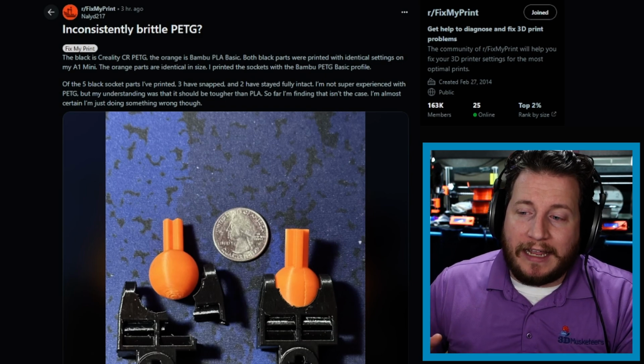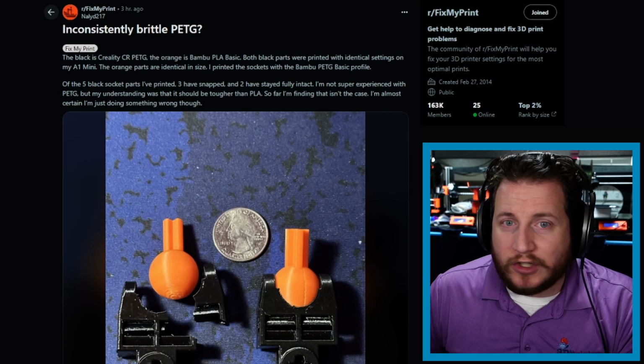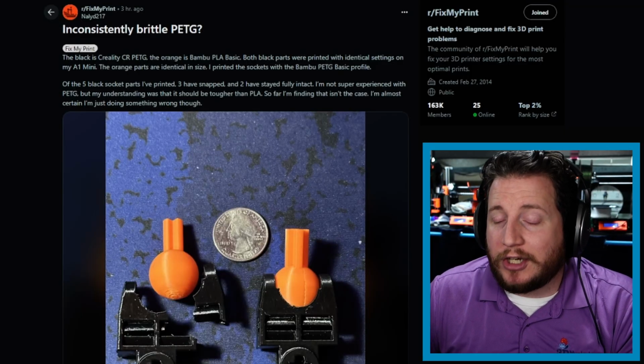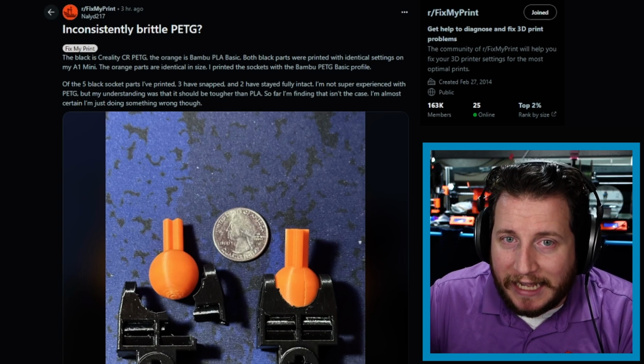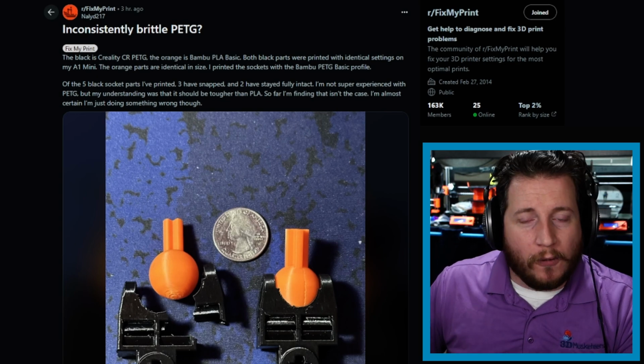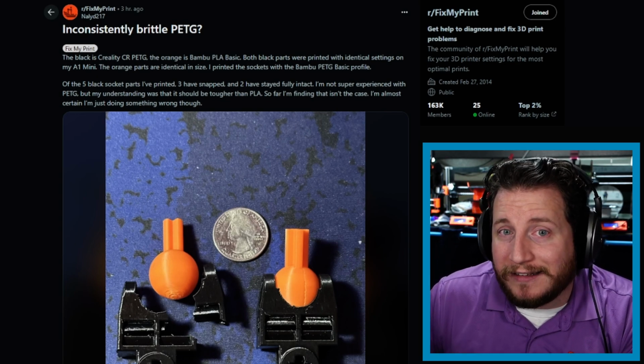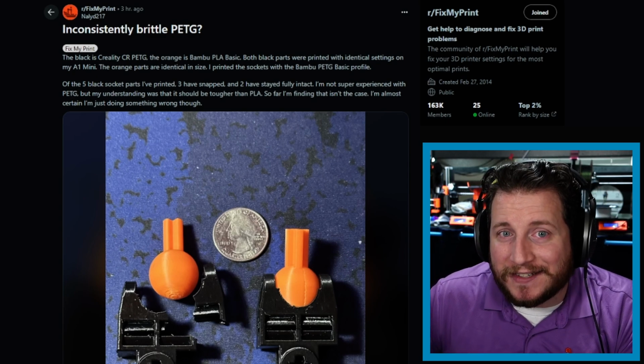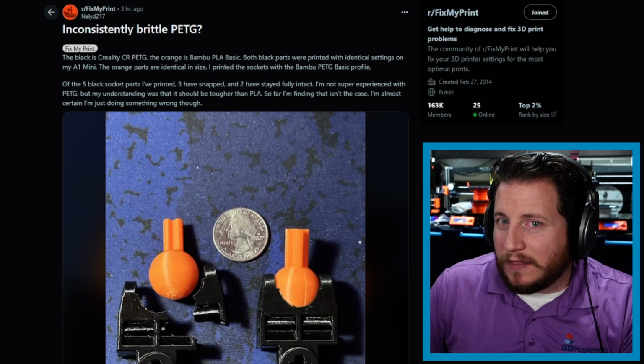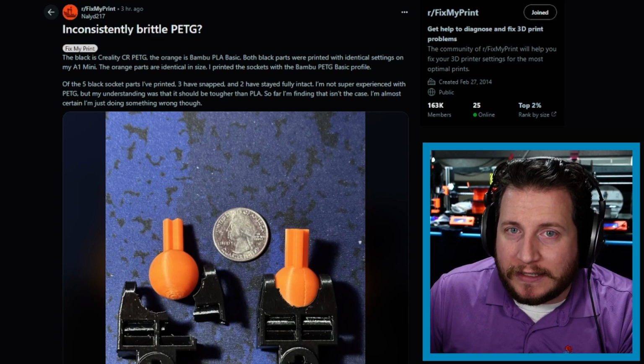occurs. So what we're looking at is a Lego ball and socket joint from the Technic set, at least from my relatively inexperienced Lego stuff, so Lego nerds, let me know in those comments. But we've got PETG. Being PETG, it tends to fracture before it yields, and that is why Lego is made out of ABS, because ABS tends to stretch and yield a little bit elastically and then inelastically before it completely fails. The way to deal with this, at least on the PETG side, is print hotter.